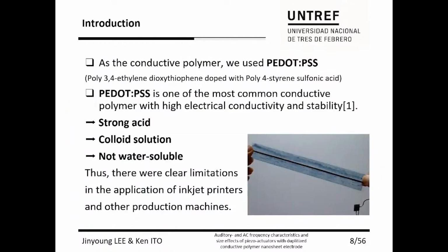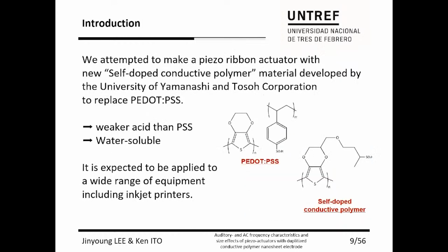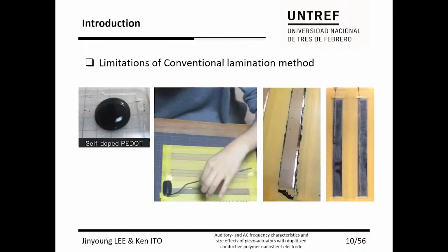Still, there are some problems with conductive polymer. We use PEDOT:PSS, which is a strong acid colloid solution and insoluble. Instead of PEDOT:PSS, we use self-doped conductive polymer, which is weaker acid and water-soluble. We tried to make a piezo ribbon actuator with this new polymer, but because of its soluble characteristics, we couldn't laminate this on the surface of water-repellent plastic film.